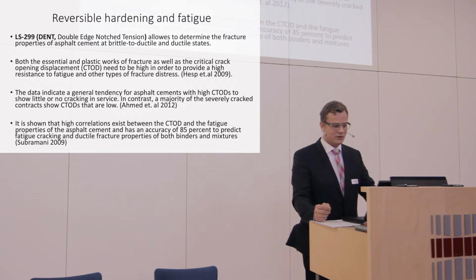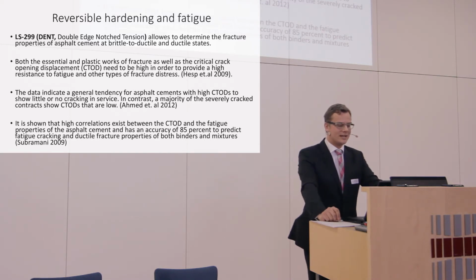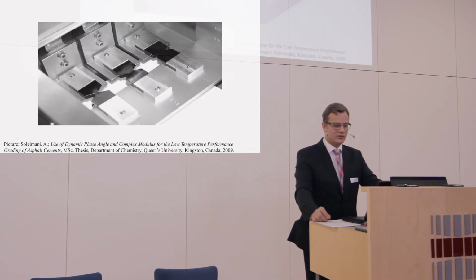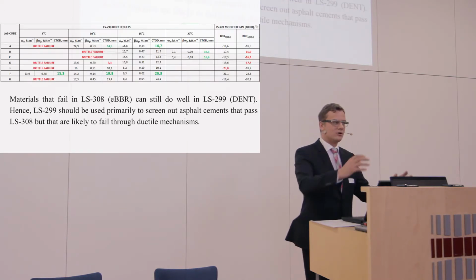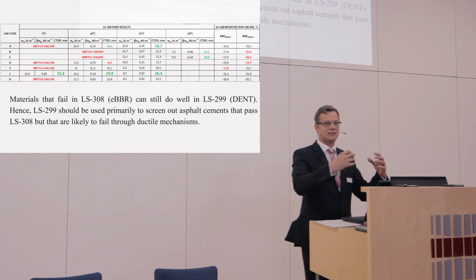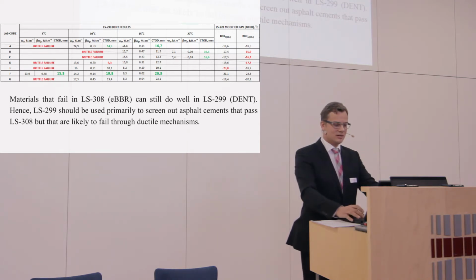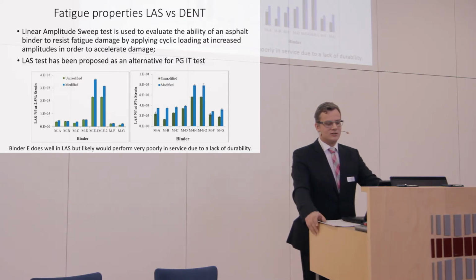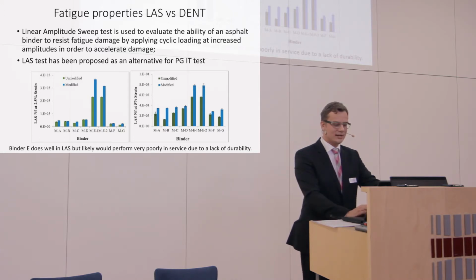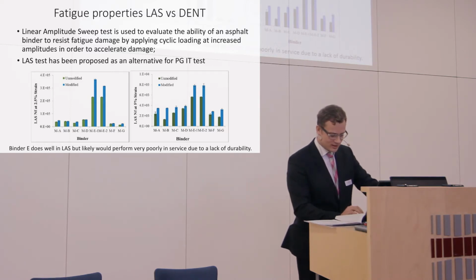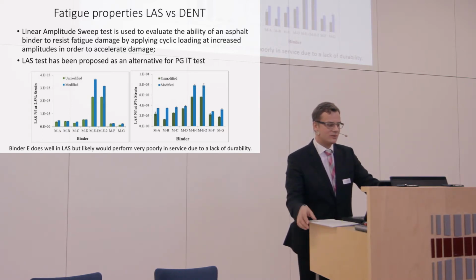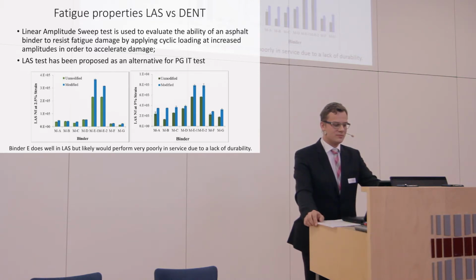We have done reversible hardening and fatigue study also with double-edge notch tension test, LS299 or DENT. It also shows very good correlation between how binders are acting on a field and how binders are acting on these tests. DENT is considered as one of the tests for fatigue properties, and also Professor Bahia told a little bit about LAS, or linear amplitude sweep test, which is also used for fatigue properties.